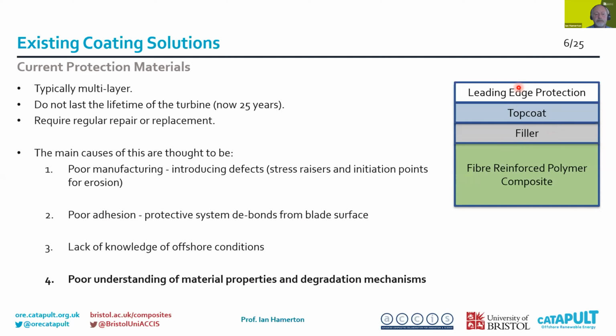Transmission properties differ greatly. So we're designing this structure to last some 25 years, and the materials that we're putting onto those structures don't have that sort of lifetime in pristine form. So regular repair, replacement is inevitable, and so consequently what we're trying to do here is to have a greater understanding of the materials that we're using, and as a consequence improve the modeling methods to understand the lifetimes of those materials, and to try and understand more about when those materials might usefully be repaired or usefully reduced or removed from service to enable replacement to take place.